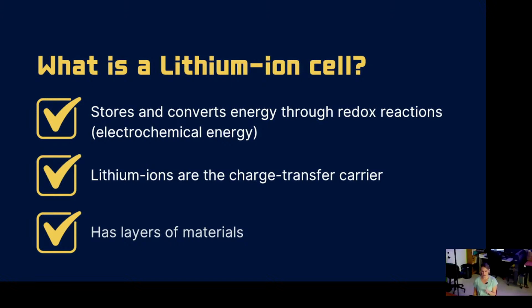Typically, the slowest step is the diffusion of lithium ions through the particles of the electrode or through the electrolyte itself, especially if it's a solid-state electrolyte material. I like to think of the lithium moving through the cell as going through an obstacle course. At different parts, whether through the separator or through the electrodes or wherever it may be, there's a different obstacle and a different rate that it moves through. But actually the redox reaction is the quickest part. That's electron fast, you know? So good question. Any other?